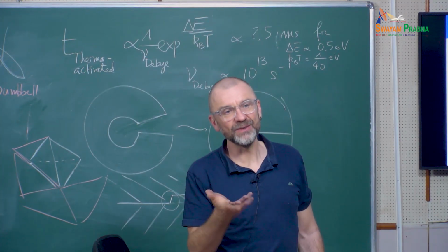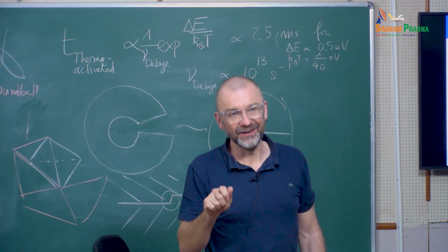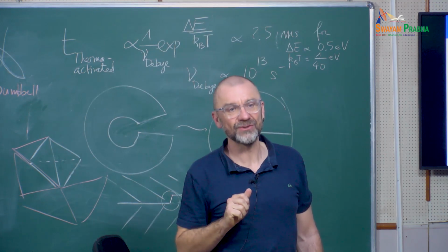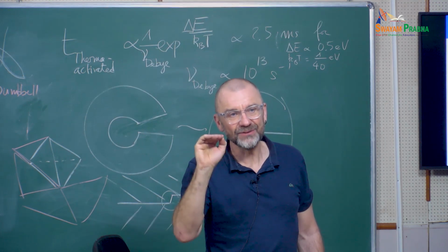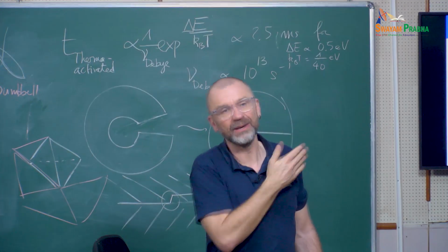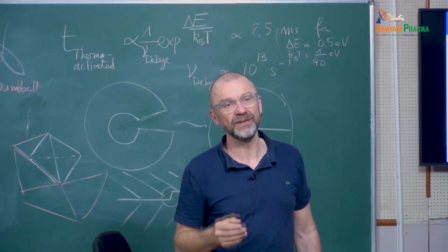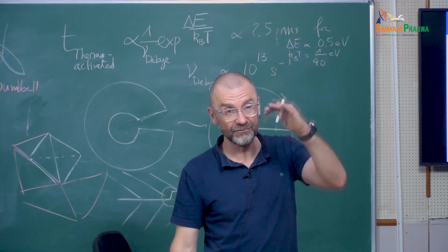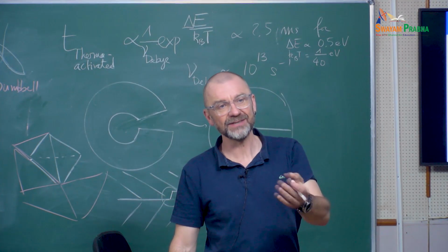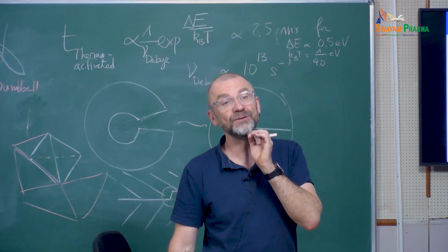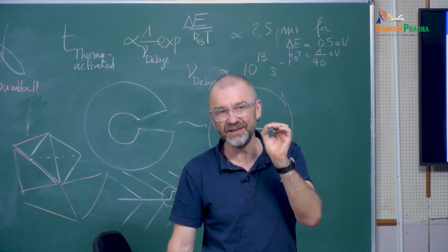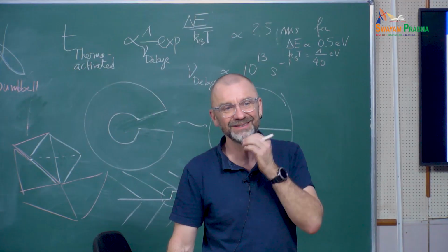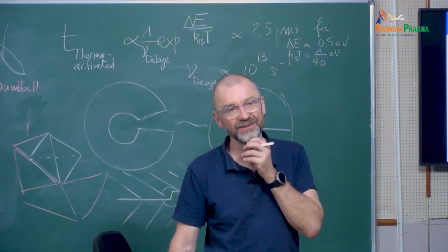You can always, with dislocations or with cracks, play with the applied stress to be close enough to the resistance of the lattice, the Peierls stress, to see the dislocation moving, but you're not in realistic conditions then. But for vacancies, for example, if you apply a stress, you can change a little bit the diffusion barrier, but not much. And so there, with brute force MD, there's nothing you can do.